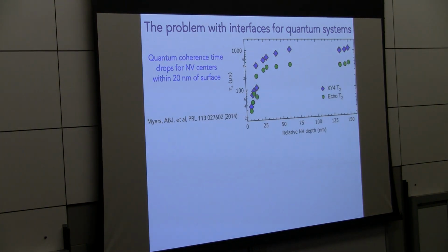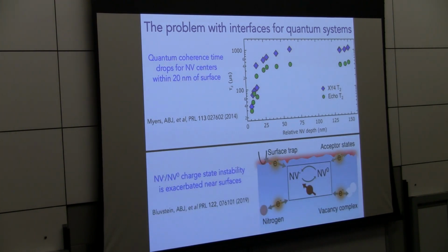For NV centers in particular, several years ago we mapped this out quantitatively by measuring the quantum coherence time of the NV center, which is something we want to keep high, as a function of depth below the diamond surface. For here, just focus on the green data points, which show the Hahn echo T2 time measured for NV centers as a function of depth. Once you bring the NV center within about 20 nanometers of the surface, the coherence time starts to drop. So that makes it not a great sensor. Another thing that can happen with NV centers near surfaces, and I won't talk so much about this, just to say that this is yet another surface-induced problem, is charge state conversion.